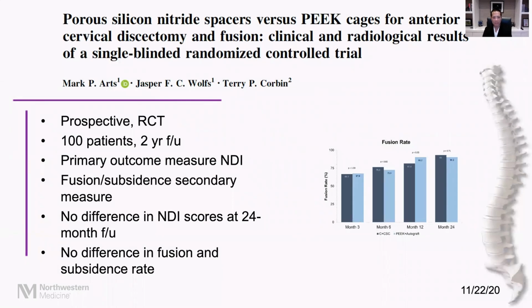However, the evidence behind silicon nitride for the cervical region is sparse. The best data that we have available compare silicon nitride to PEEK cages and conclude that there is really no difference in fusion or subsidence rate. There are no superiority studies, and it's difficult to determine whether or not the integration of this component is real when it comes to in vivo use.